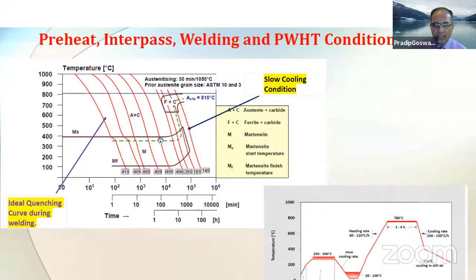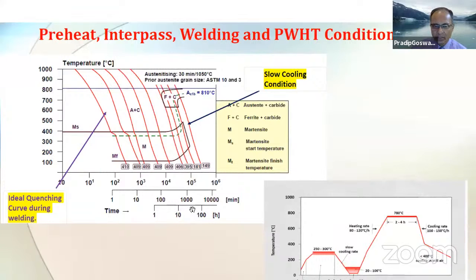Here I've just tried to capture the continuous cooling diagram and the post-weld heat treatment cycle side by side, for better understanding. So when you talk about the cooling rate from the welding temperature, following welding, if one is cooling this alloy to the ambient or room temperature, one can expect this level of hardness, typically 400 and above, in Vickers, I would say.